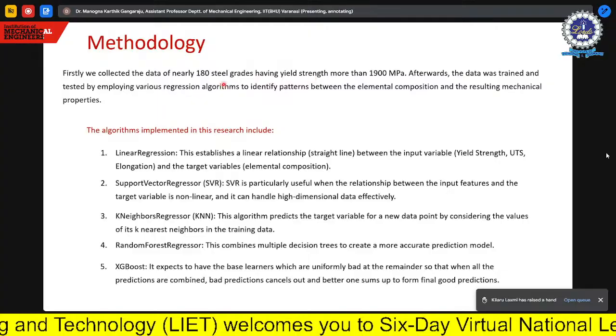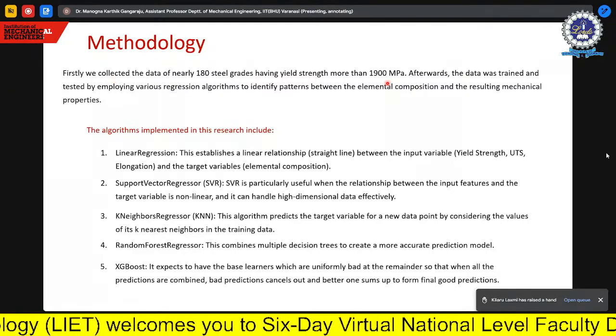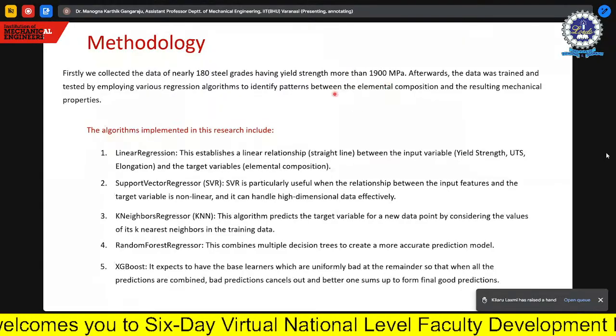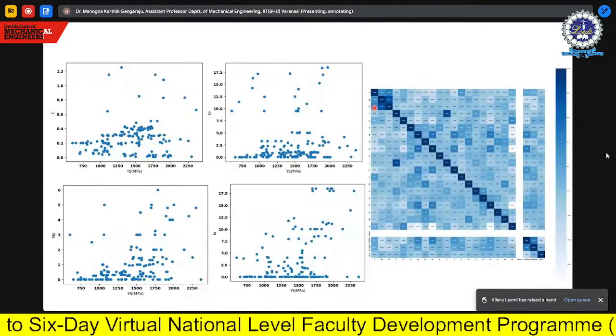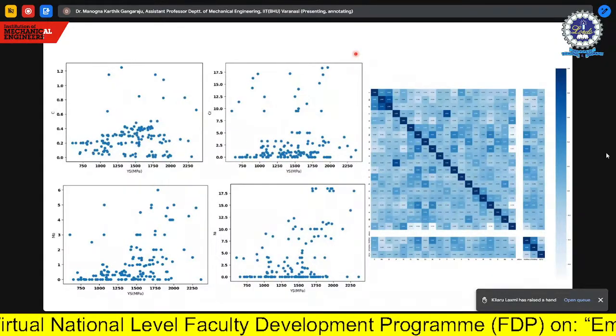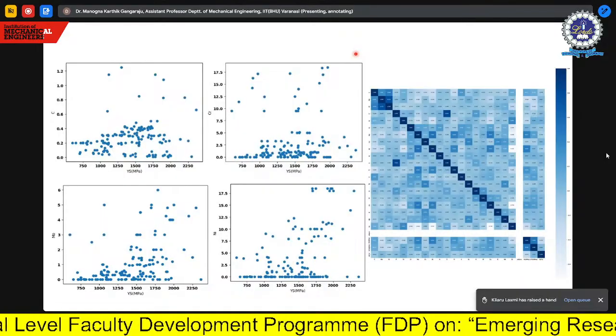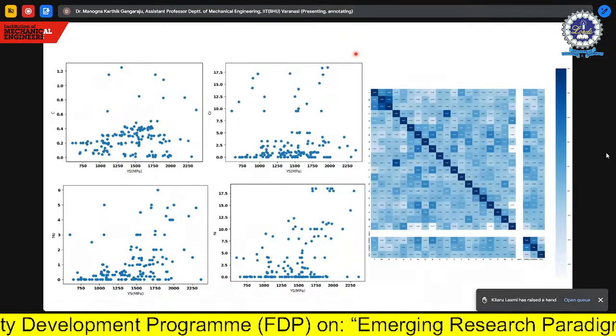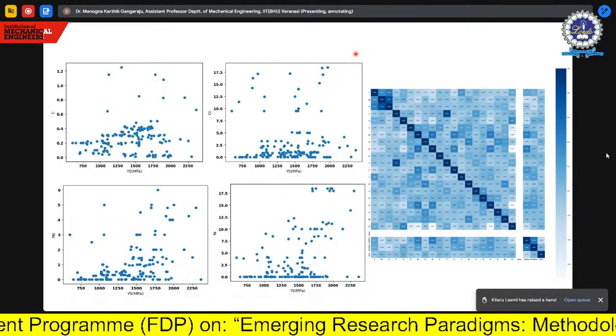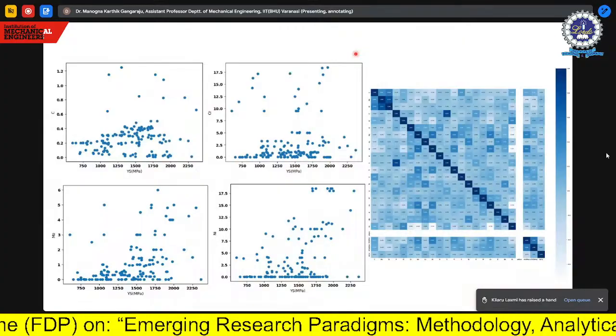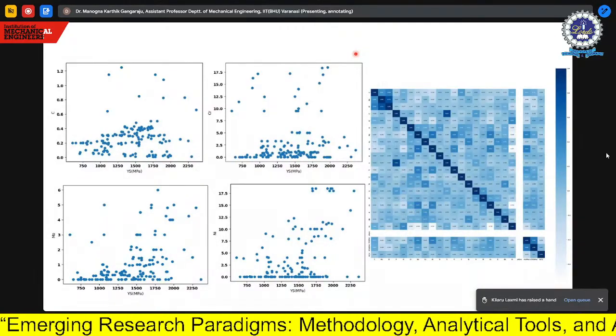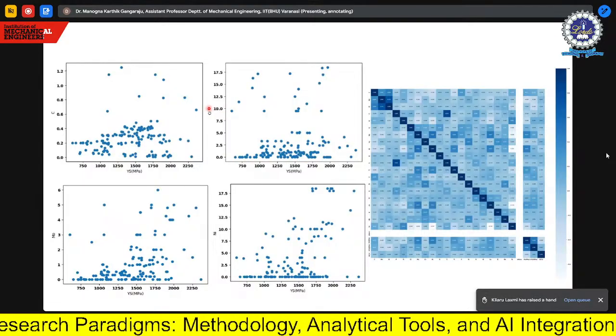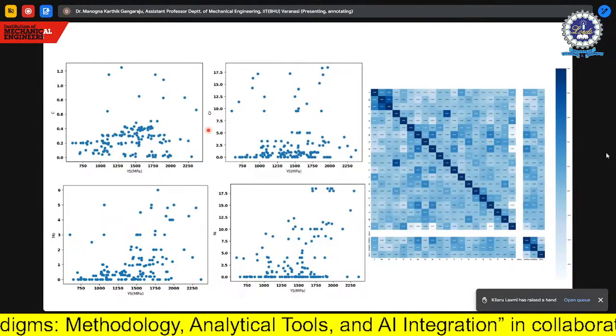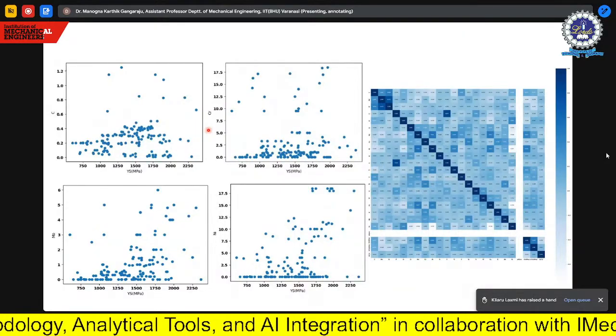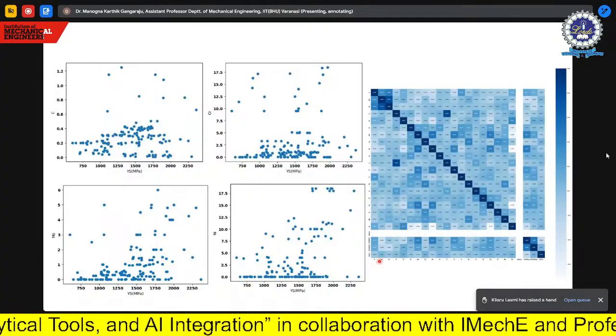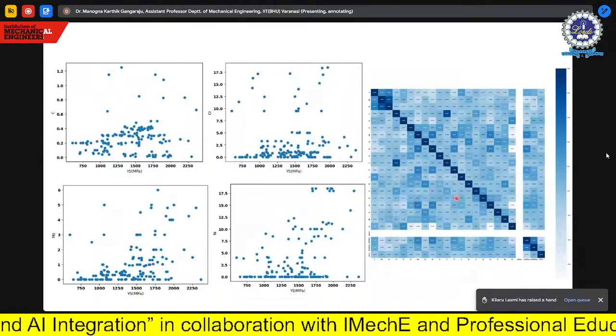So we have several data sets. When we collected data for more than 1900 megapascal yield strength, we took close to 180 data sets. The whole idea is you need composition: which composition of my material will give me yield strength greater than 1900 is what we wanted. So the model is developed to predict which composition will give this. We collected all this data, and saw that there are some elements which are mandatory or definitely required to achieve that. So we do this mapping of different elements and their requirements.